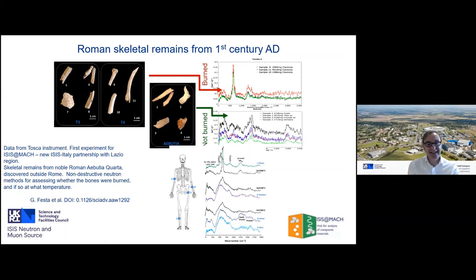They have realized that there's a very clean signature in inelastic neutron scattering, which relates to the temperature at which bones were burnt. So if you want to understand the funereal processes that took place in the first century AD, inelastic neutrons can give you a key here. What these guys realized is that when you burn a bone, the bone matrix undergoes some structural and dimensional changes, which make it very difficult to use more conventional osteometric methods. So what they did was to combine inelastic neutron scattering, Fourier transform infrared, micro-Raman, and so on, to look for the signatures which allow you to differentiate bones that are burnt at 400, 500, 800 degrees C, and so on.